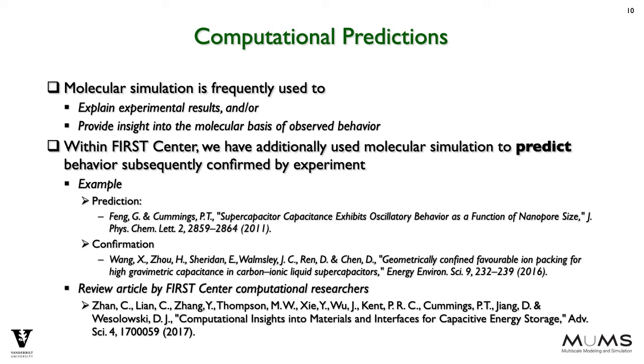Inspired by the experiments of Yuri Gogotsi and Patrice Simon, showing that carbide-derived carbons with EMIM-TFSI ionic liquid electrolyte exhibit a peak in capacity as a function of carbide-derived carbon pore size at 0.7 nanometers, we performed molecular dynamics simulations that confirmed this peak, provided mechanistic understanding of its origin, and additionally predicted the presence of peaks at pore sizes of 1.4 nanometers and higher. This computational prediction was reported in the paper by Guang Feng, shown here. This prediction was finally confirmed 5 years later in the paper by Zhuhang Wang and co-workers. A review of the computational research in the FIRST Center up until 2017 is provided in the Advanced Science review article given here on this slide.